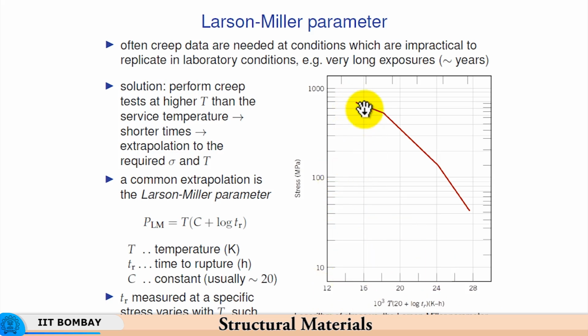One can plot the stress here, and then you see three discrete zones in terms of rate of decrease of stress. So, the stress capability is reduced with increasing Larson-Miller parameter. For a given Larson-Miller parameter, say 16,000, various combinations of temperature and time to rupture which give me the same Larson-Miller parameter will result in the same single value of stress capability.